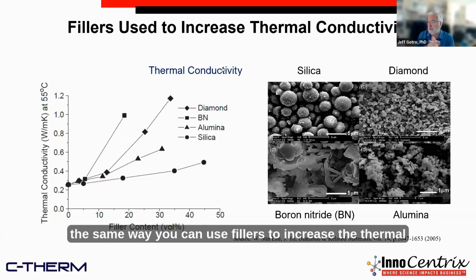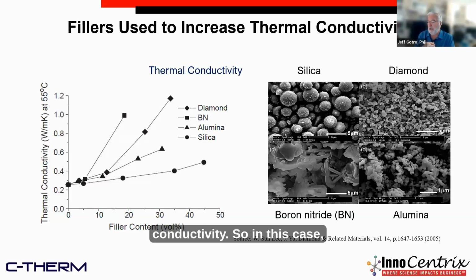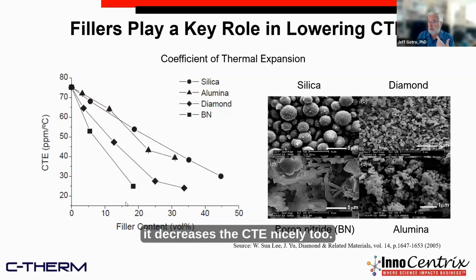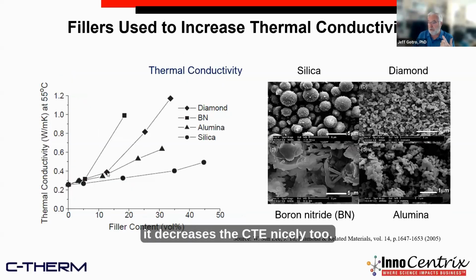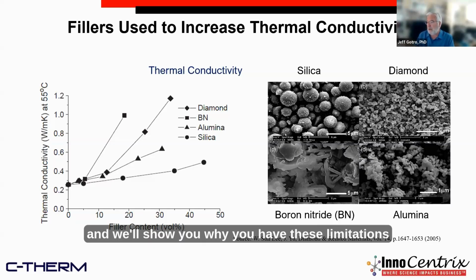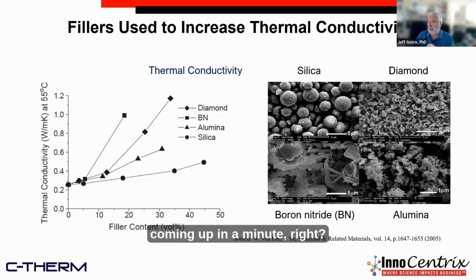In the same way, you can use fillers to increase the thermal conductivity. So in this case, silica is not very good at increasing thermal conductivity, whereas boron nitride, the square here, is very efficient at increasing the thermal conductivity. So one of the things you could say is, well, let's use boron nitride because, number one, it decreases the CTE nicely. Two, it increases the thermal conductivity, right? Well, that works to a point, and we'll show you why you have these limitations coming up in a minute.